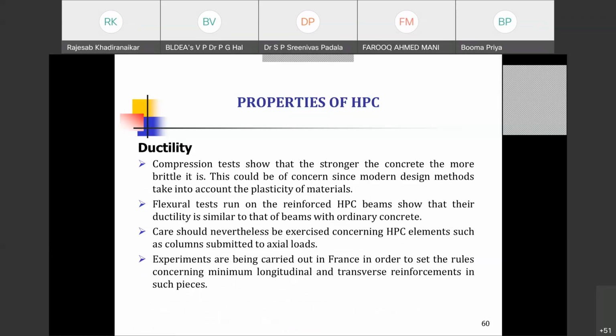And coming to ductility, the general notion is that as the strength increases, it becomes brittle. That is true also. The compression tests show that the stronger the concrete, the more brittle it is. And this could be of concern since modern design methods take into account the plasticity of materials. The flexure test run on the reinforced HPC beam shows that the ductility is similar to that of beams with ordinary concrete. So the material alone may be a bit brittle, but when you do the design and do proper detailing, then whatever level of ductility you want to imbibe in your structure, that is possible.